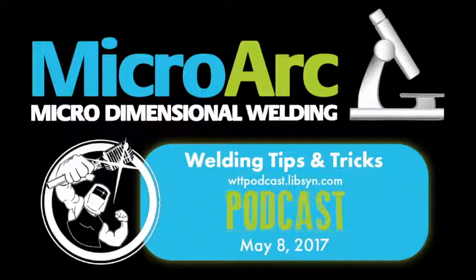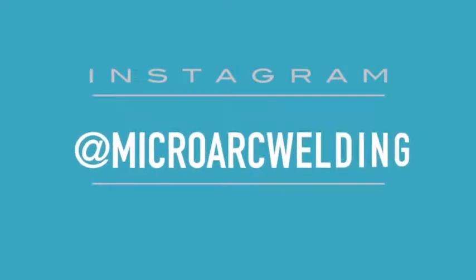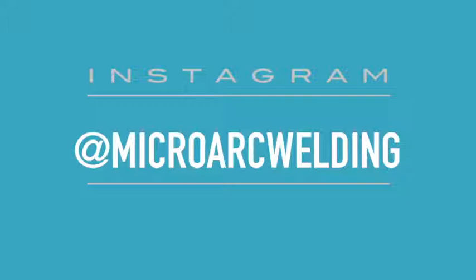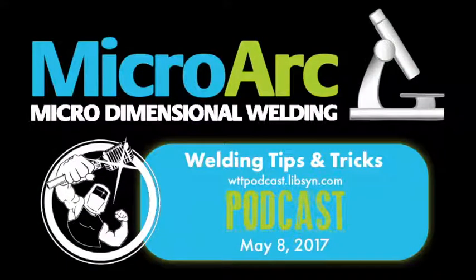I'm right with you, because I always felt like there's benefit to lighting up on a clean piece of copper and bringing it up to a certain level, letting anything that's on that electrode, any foreign matter, any hydrocarbons or anything from any acetone or mineral spirits that were on a part, get smoked off. Then you let it cool, and it cools under an argon atmosphere. Now that's a good surface to get a good crisp start on after you do a burn off pass on some clean copper.